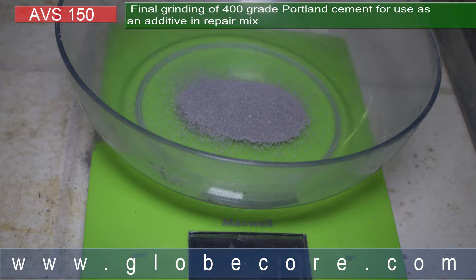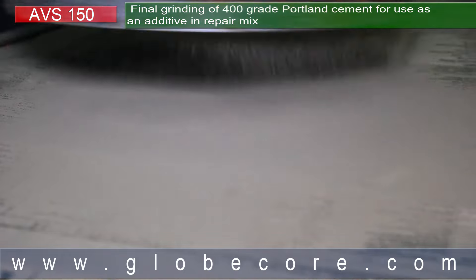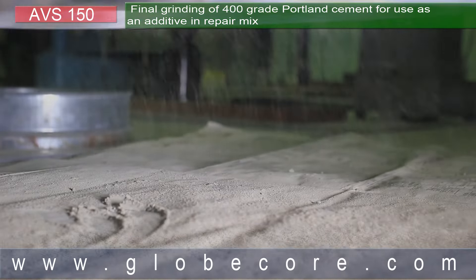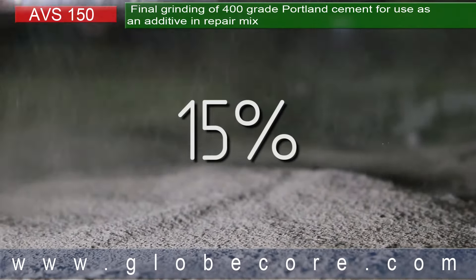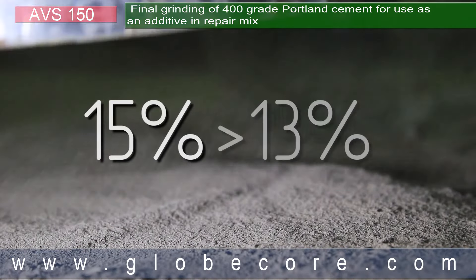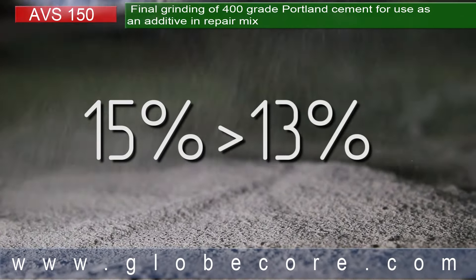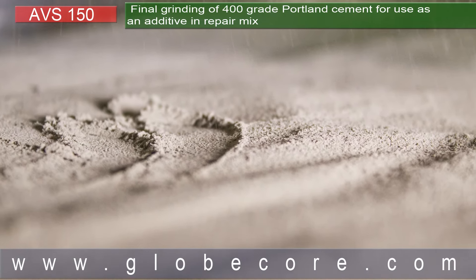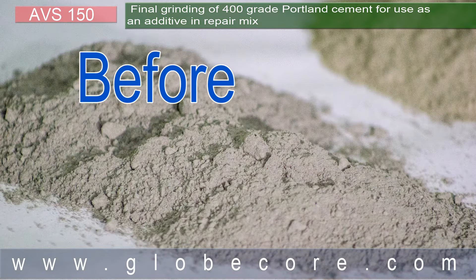All of the material passed through both sieves, while the 0.04 sieve captured 13 grams of the material — that is, 13% of the total mass. A manual 1-minute rescreening on paper, with the bottom removed, was performed. According to standard, the allowable portion is 15%, 2% more than what we received.